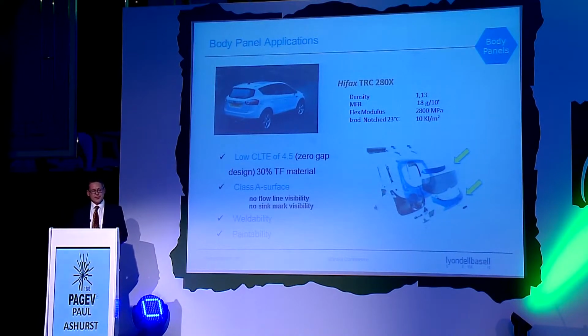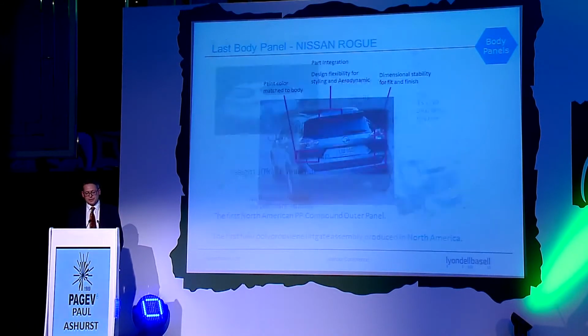Body panels is an area of growth, as we've seen already. We're supplying the material for the outer panel and also the roof spoiler. What are the requirements? Low CLTE, so we're talking about low shrink materials, and that's because these polypropylenes shrink quite a lot, but they're in contact with steel, so you don't want to create any gaps between them. So this is a 30% talc-filled material, so it's relatively low shrink. And these materials also have to have no flow lines visible and no sink marks visible, because most of these parts are painted, so you have to have a Class A surface finish. This material is high rigidity, easy flow, and our CAE engineers based in Italy worked very closely with our customer to achieve a really superb surface finish.